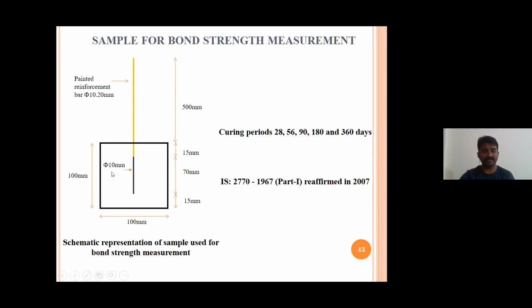Remember that the bar diameter that we have used is 10 mm. This is the schematic representation of the sample used for bond strength measurement. The top length we have kept 500 mm because our UTM was very long, so we had to use 500 mm length. So these are the specifications which are mentioned in the IS code for testing the bond strength of reinforced concrete.